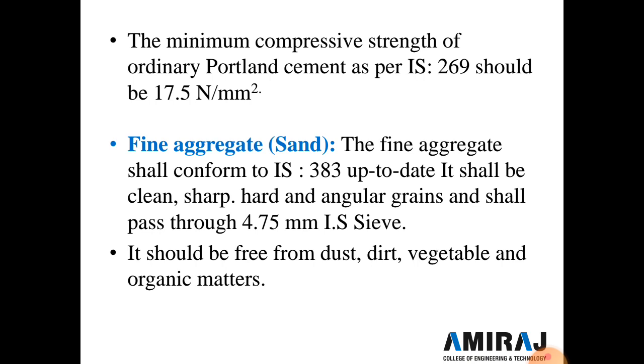The next material we use in RCC work is fine aggregate, as sand. Fine aggregate shall conform to the up-to-date IS 383, and this sand is clean, sharp, hard, and angular grain, and shall pass through the 4.75 IS sieve. It should be free from dust, dirt, vegetable, and organic matter. And generally sea sand shall not be used.